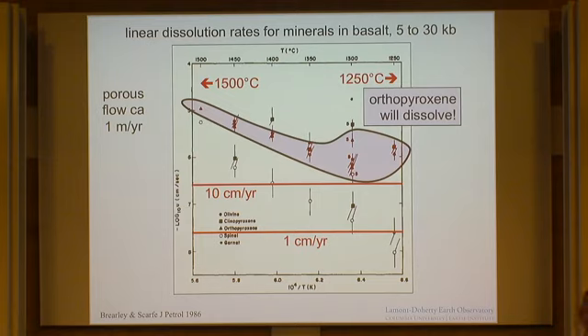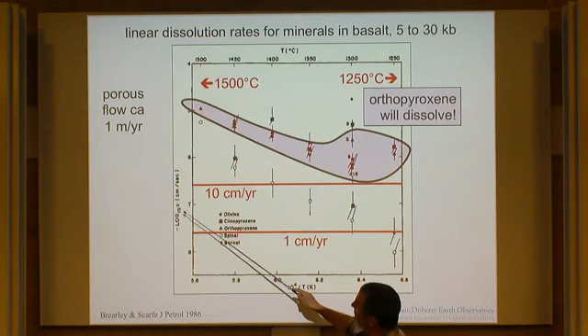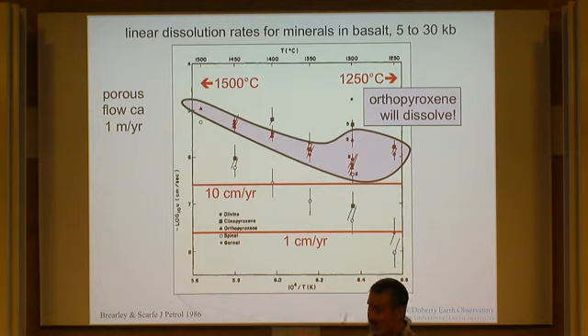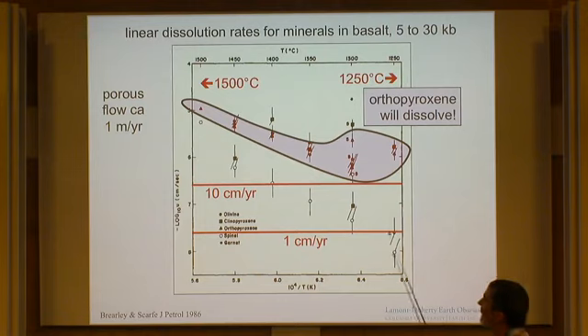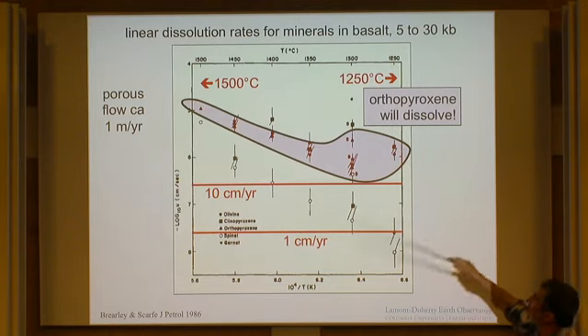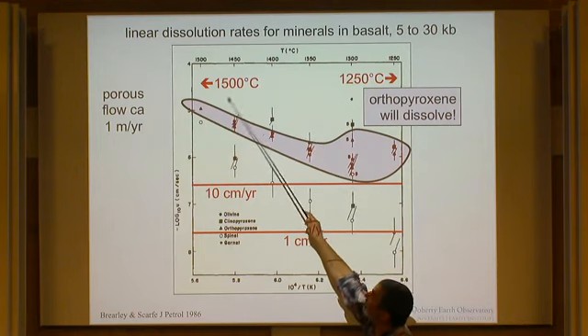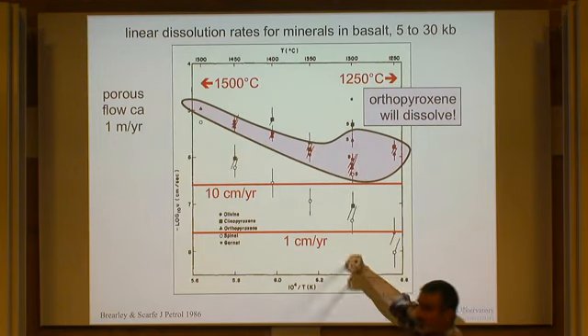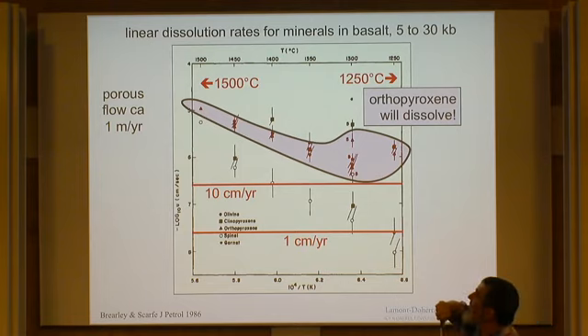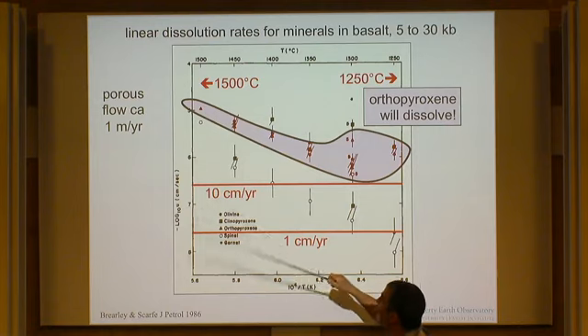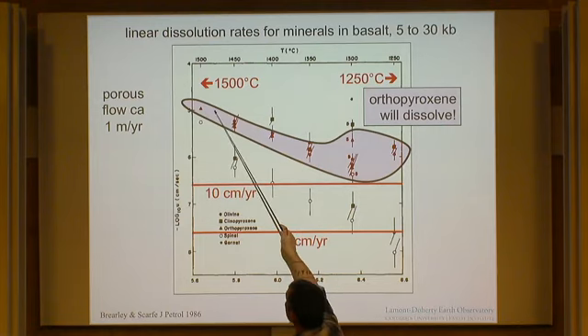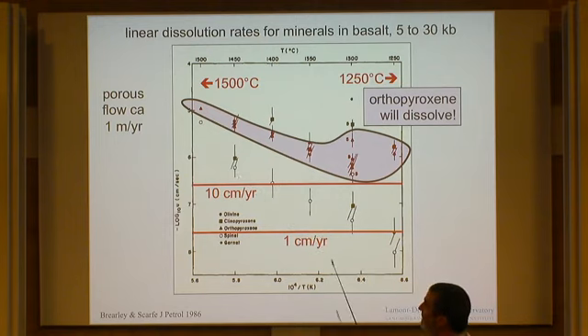And they can't do that by porous flow. These are dissolution rate data, summarized many years ago by Brearley and Scarfe, in log centimeters per second, linear dissolution rates, crystal dissolving inwards towards the center. I've highlighted dissolution rates of the mineral orthopyroxene, over a range of temperatures from 1500 degrees on the left to 1250 degrees on the right that are appropriate for upwelling mantle beneath mid-ocean ridges and other places too. You see that the velocities are in excess of 10 centimeters per year.